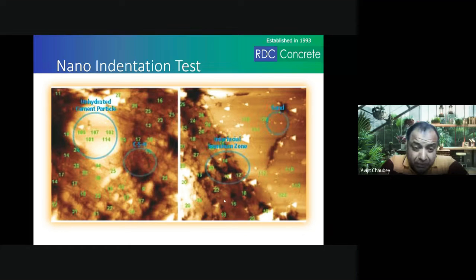So basically, when you are getting higher strength at a lower water cement ratio, expect that at low water cement ratio, the CSH gel formation will be much less as compared to a higher water cement ratio. When the water cement ratio is 0.5, you will have more of CSH paste. And when the water cement ratio is 0.2, the CSH gel would be much smaller.